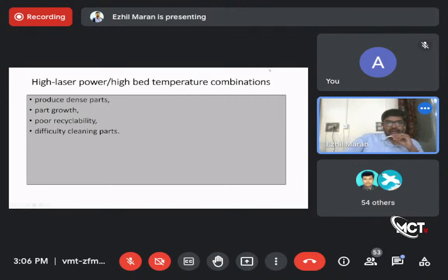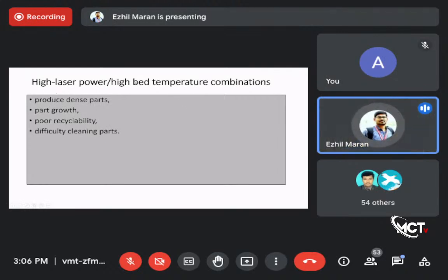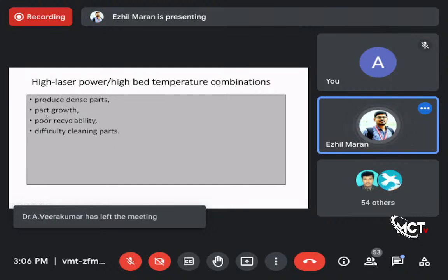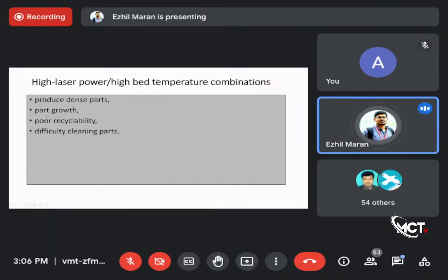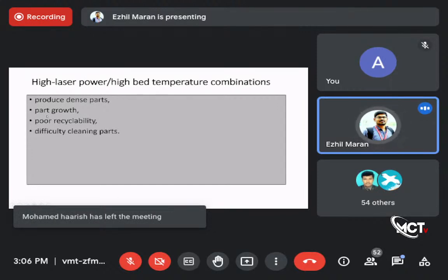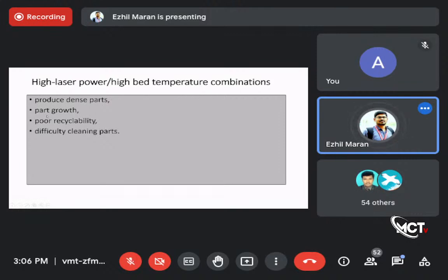This is the relationship between laser parameters. If you use a combination of high laser power and high bed temperature, you can produce dense parts, but part growth, poor recyclability of the powder and difficulty in cleaning parts occur. There are pluses and minuses. Producing a dense part is positive, while part growth, poor recyclability and difficulty in cleaning parts are on the negative side. If you use a combination of low laser power and low bed temperature, you cannot get a dense part or a structurally reproducible one. At the same time, better dimensional accuracy is there. There is a tendency for layer delamination. Delamination means layers will peel off. Low laser power and low part bed temperature combinations cause non-uniform buildup of residual stress and curling of bonds.